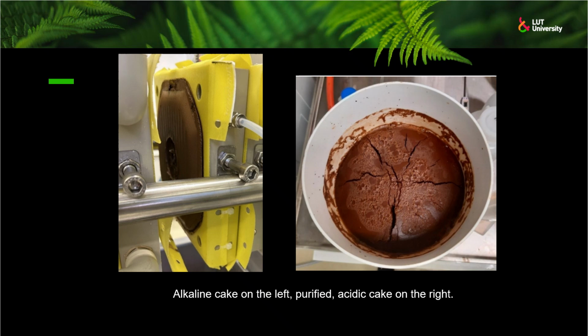Cake formation. Alkaline cakes were formed under pressing in a laboratory filter press. The purification stage was done in a Büchner funnel without pressing. This led to a significant amount of carryover in lignin samples. The Büchner funnel was used because the volume of re-slurry was too small for the filter press.